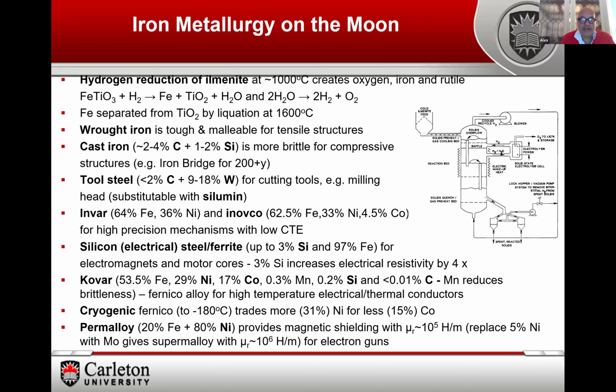The first process we want to look at is if we take one of the four minerals I mentioned, ilmenite. If you heat that in the presence of hydrogen at 1,000 degrees, you'll end up with iron metal, rutile, which is titanium oxide, and water. Then you can split that water electrolytically to recycle the hydrogen and recover the oxygen, which can be used for breathing and so on. What we're interested in here is the iron in particular, and this can be separated by liquation at about 1,600 degrees. And if we can add just a few more materials, we can get a range of different alloys for use on the moon.